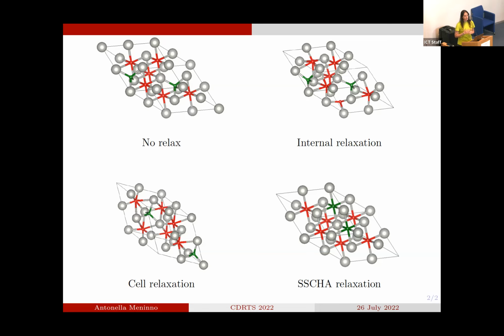And then I relax using different methods. I use two different semi-classical methods, one in which I didn't change the shape of the cell, and the other one in which I changed the shape of the cell. And then I want to compare those results with the ones that I obtained using the stochastic self-consistent harmonic approximation. Basically, what I want to explain to you in more detail tomorrow is the difference in the structure compared to the other methods, and of course this affects the electron-phonon interaction, so the critical temperature for those kinds of compounds.